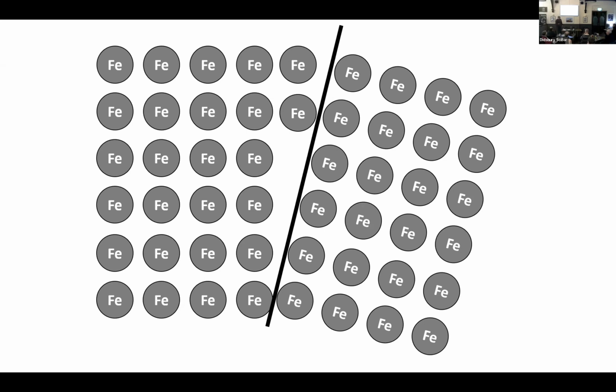So remember going back to that picture of the lamppost, and we've got different crystals. There's a boundary between those crystals, and this is another type of defect that we have, and that's fine usually most of the time. The problem is that this boundary can actually attract other types of defect. And when you start to turn this up to 11, you get transmutation. So not only do your neutrons come in, hit it, and ping off, sometimes your neutron comes in and it absorbs it. And then what you have is an unstable isotope. And then it becomes radioactive.